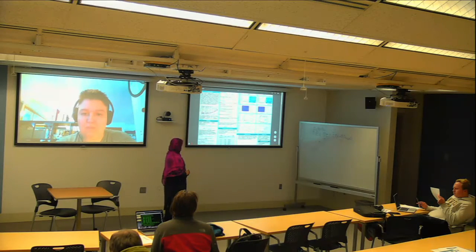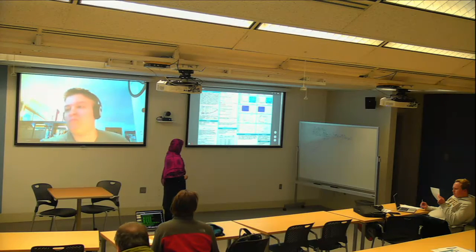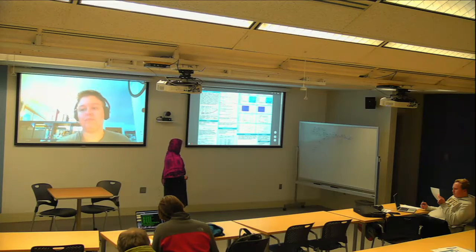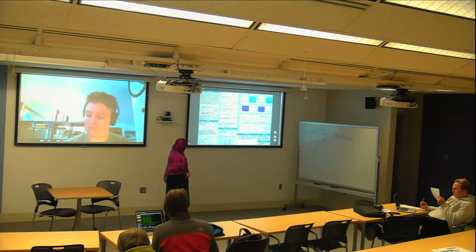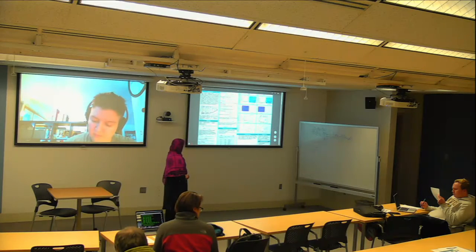For indirect transitions, relaxation is always quicker because there are some additional paths. For direct transitions, meaning momentum restricted transitions, relaxation is slower. And the energy gap law works differently for each K point.